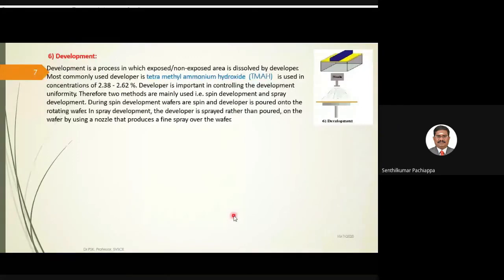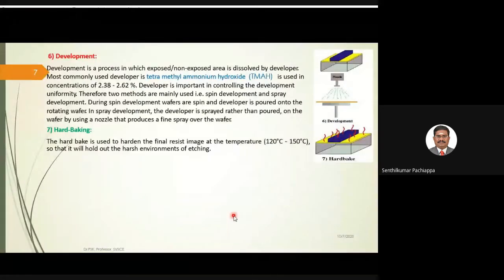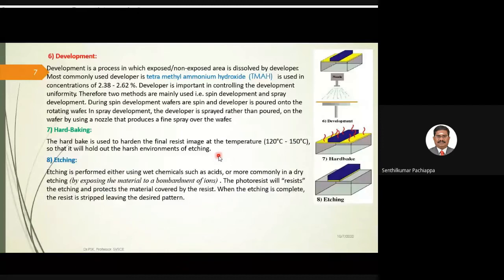So next one is the hard baking. Hard baking is used to harden the final resist image at a temperature of 120 to 150 degrees centigrade, so that it will hold out in the harsh environment of etching. Etching is performed either using wet chemicals such as acids, or more commonly in a dry etching by exposing the material to a bombardment of ions. The photoresist will resist the etching and protect the material covered by the resist. When the etching is complete, the resist is stripped, leaving the desired pattern.